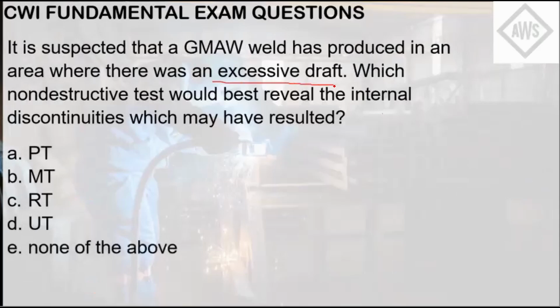Excessive drafts can blow away or remove your shielding gas altogether. This is just wind or air. If that happens, you can have internal discontinuities here. This question might be misleading. You may answer PT here, but the answer is RT, because you can remember the keyword: internal discontinuities. Those can be best revealed by RT because it's a subsurface flaw. This excessive draft can cause internal porosities, which will not be best revealed by surface detection methods like PT and MT. UT is a bit much here. It's not a thick metal that we're having to test.